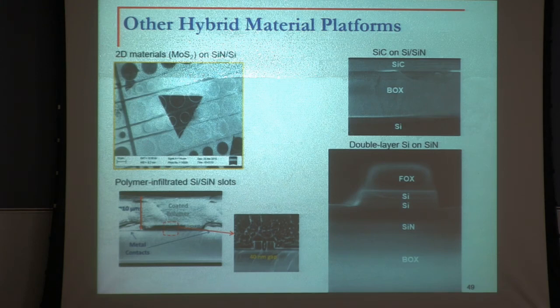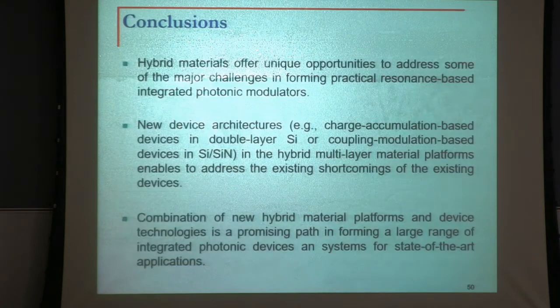I mentioned silicon carbide. This is our polymer work, where we have a silicon waveguide, etch a slot in it. It's proven that your mode can be completely or mostly confined in the slot, and then putting an electro-optic polymer and changing that electro-optic polymer through electro-optic effect will allow us to develop very fast modulators. And that's the double-layer silicon on nitride.